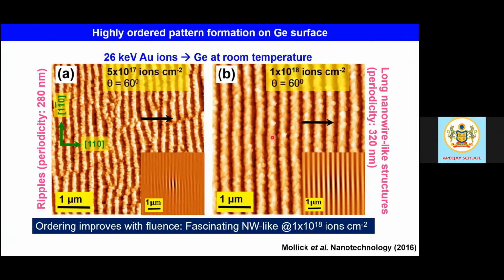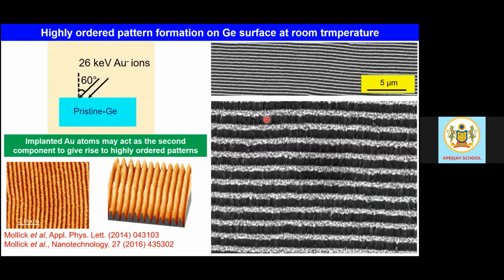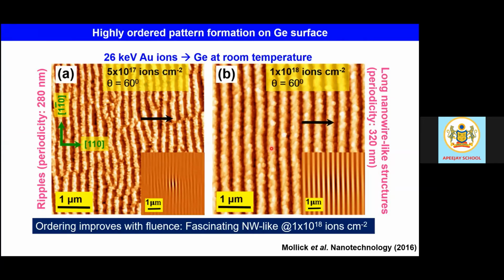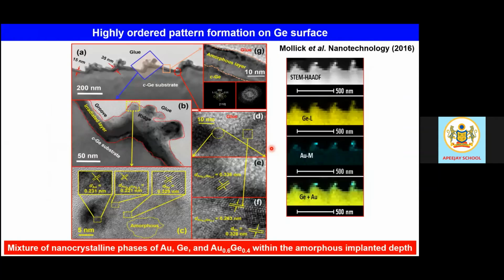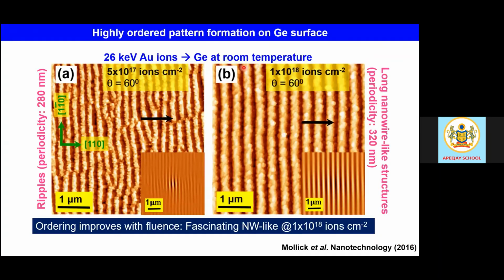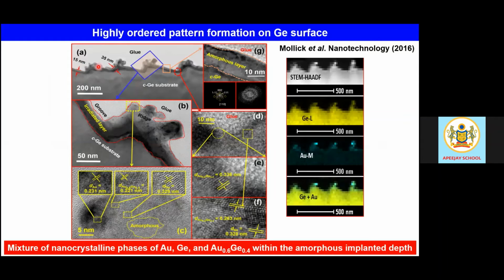And you see, let's go back to this, cone-like structures, these facet-like protruding structures we get to see very easily. The surface is very rough, which goes without saying. This gives ample indication that there are some granular kinds of things. When we take the help of cross-sectional transmission electron microscopic measurement, we see that flower-like structures are seen at the top of these ridges. These are the pattern ridges, and these white objects are sitting there. These are the flower-like objects that we see very nicely, very periodically located.